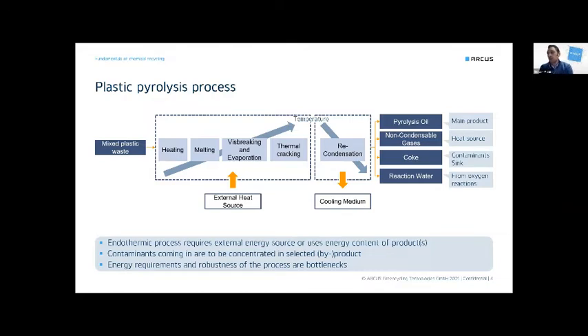Most of the time you also produce some reaction water. It comes from reaction with oxygen, specifically if you have oxygen-containing polymers like PET. An important thing to mention here: pyrolysis or chemical recycling is an endothermic process, so it requires external energy, which can be from the grid or from using one of the products you have during the process. And as probably you all know, the energy requirement and the robustness of the process are the main bottlenecks to establish such a process.